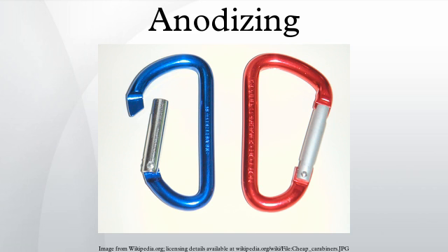Integral color anodizing is generally done with organic acids, but the same effect has been produced in laboratory with very dilute sulfuric acid. Integral color anodizing was originally performed with oxalic acid, but sulfonated aromatic compounds containing oxygen, particularly sulfosalicylic acid, have been more common since the 1960s. Thicknesses up to 50 µm can be achieved. Organic acid anodizing is called Type IC by MIL-A-8625.